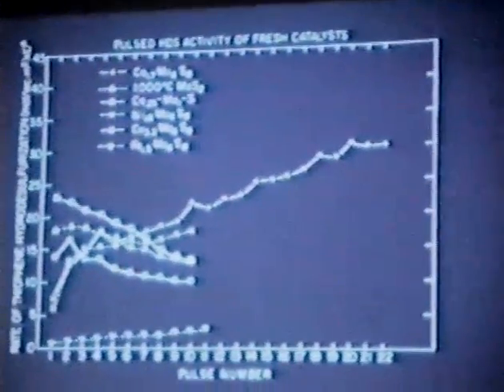What we think this really is, again, a surface oxidation of this cobalt Chevrel phase, in which we are forming MoS2 on the surface of this catalyst, okay? And this is one of the few catalysts that appears to do this. But the small cation Chevrel phase materials are materials in which there's a good deal of delocalization of the cation. There's mobility of the cation. And what we think is happening here, and XPS confirms this, and Auger confirms it, is that there's a retreat of the cobalt away from the surface in some of these compounds, and you tend to form MoS2 on the surface. And that may be the reason why this catalyst looks like it activates.